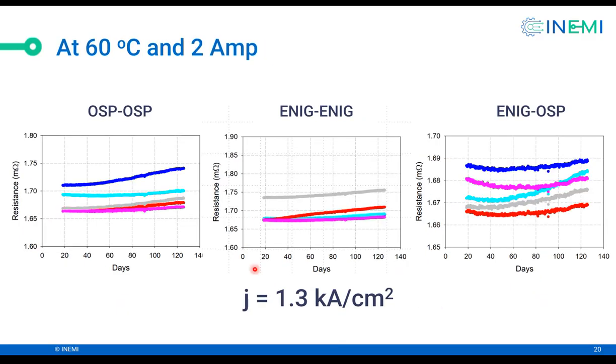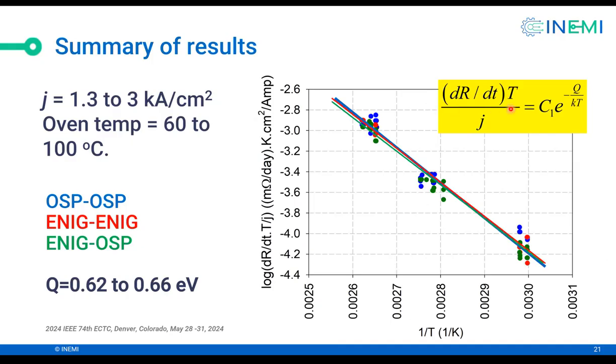And so previously it was 100 degrees, now it's 60 degrees at 2 amps. So low temperature, low current. And now the dip lasts a long time. So we have to wait for a very long time to get the linear region at low temperatures and low currents. Anyway, so here are the results.